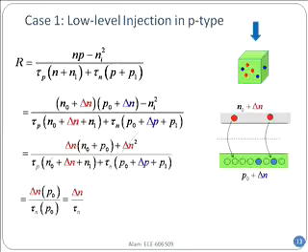But at the end of the day, look at that expression, delta n divided by tau sub n. So how will it decay as a function of time? This is dn dt, right? That's the rate of change. It's proportional to delta n over tau n. So it will go down exponentially as a function of time, right? That is how it is going to decay.